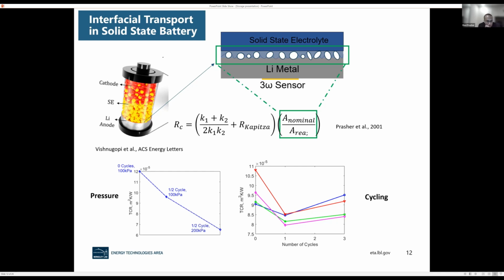I spent my early career after my graduate school at the chip making company Intel, doing electronics cooling. So I really looked at a lot of interface materials and interface phenomena in chip cooling. So just realize that the lithium metal solid electrolyte interface is very similar to a chip in contact with a heat spreader, right? So you can calculate the contact resistance, which depends on the nominal area and the real area. Real area is smaller because you have voids, right? Now again, we are doing this thermal wave sensing, measuring this contact resistance directly from the thermal wave sensor. And this A nominal and A real depends on pressure.